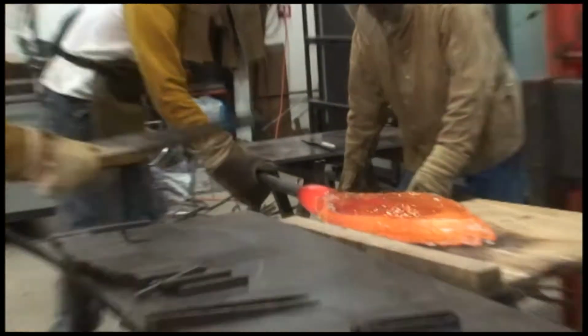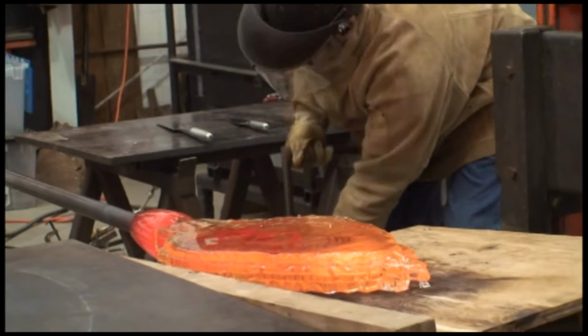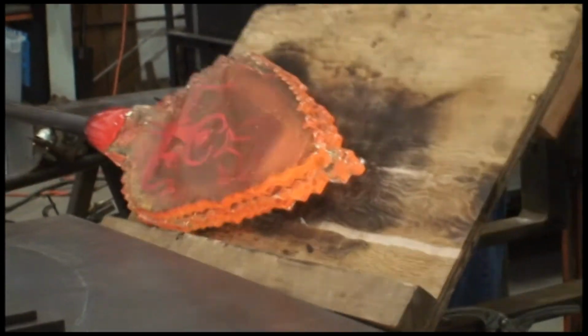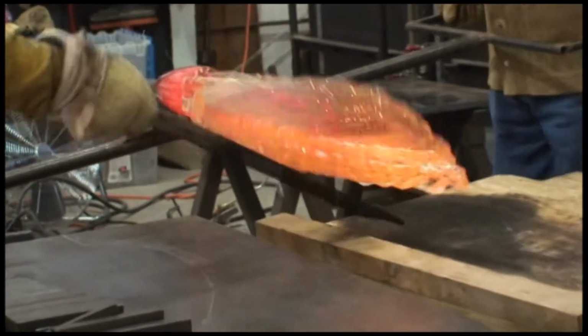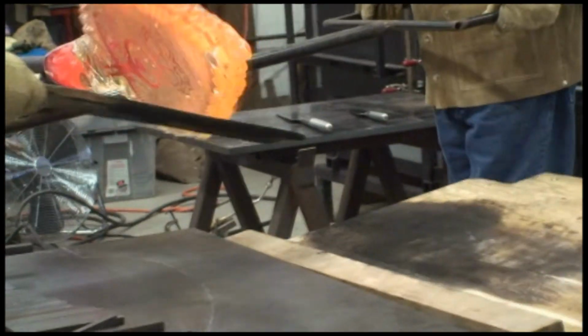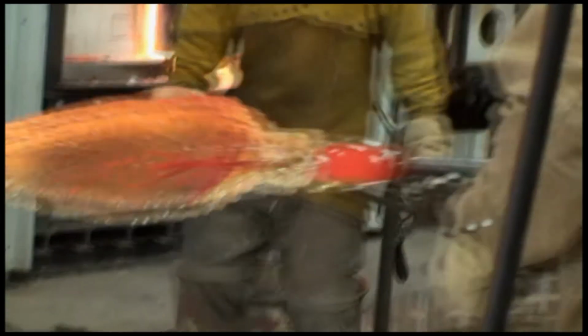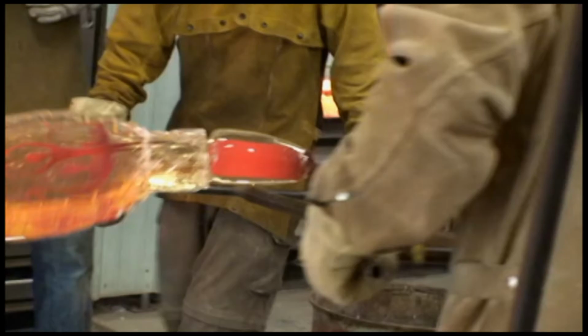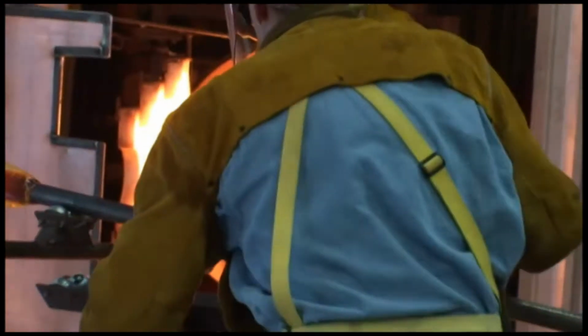In fact, here's what happened the last time we tried this. The touchdown points aren't hot enough, and the body of the casting is too cool. It looks plenty hot, but you can see how much trouble we're in. This glass sculpture has large cracks in critical spots, right here. We wrestle this piece to the glory hole, but before we can reheat or stabilize the sculpture, all hell breaks loose.